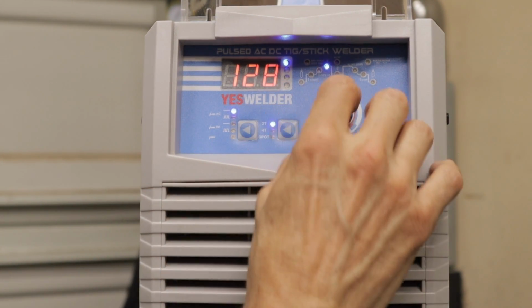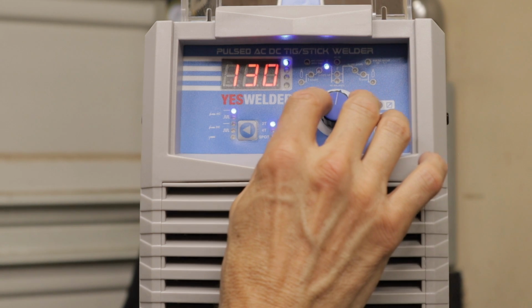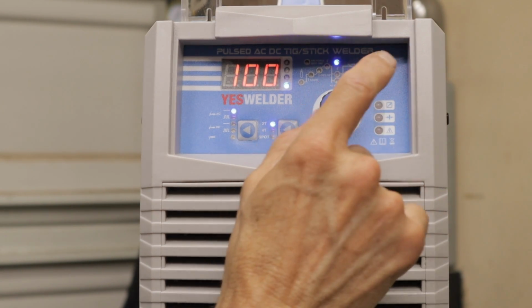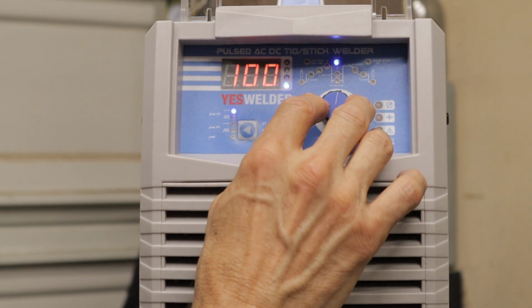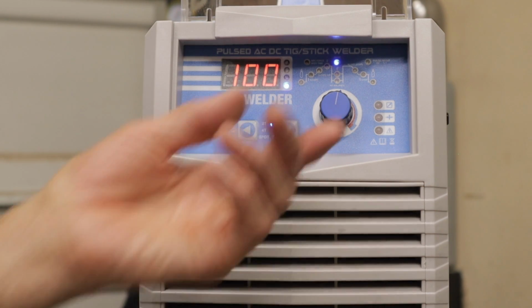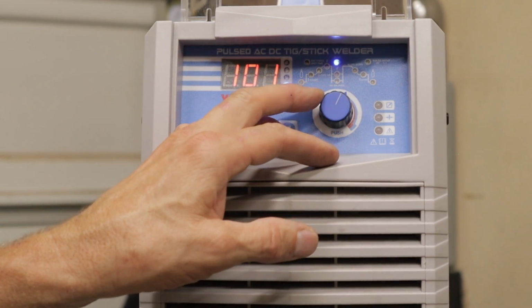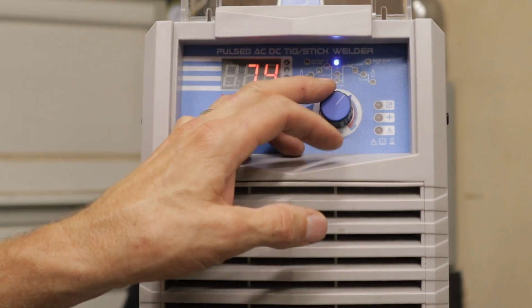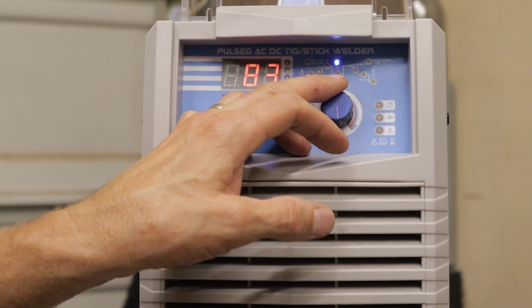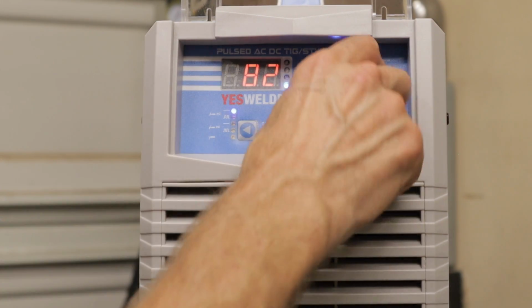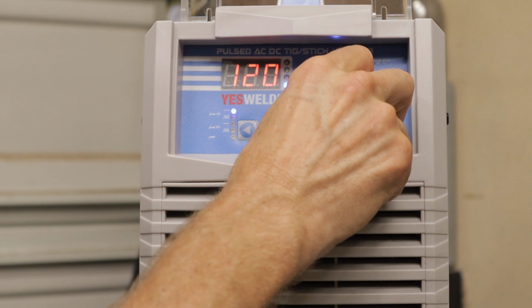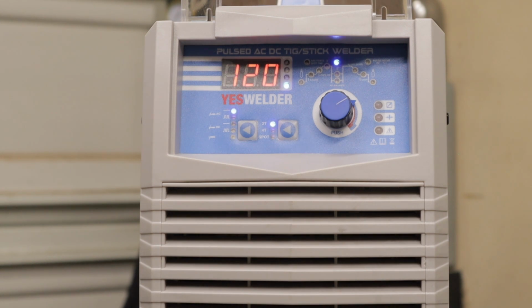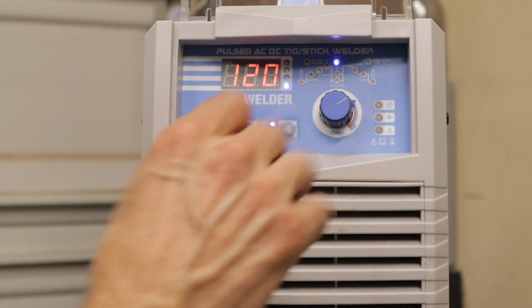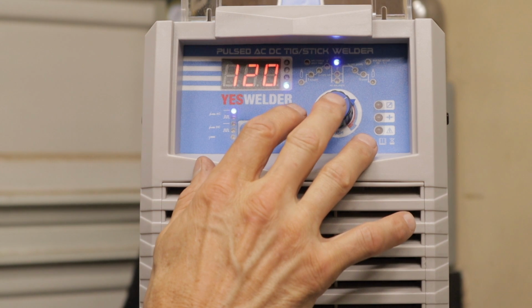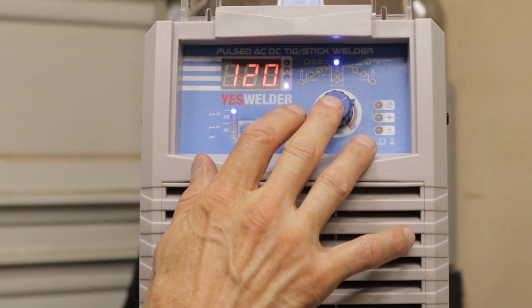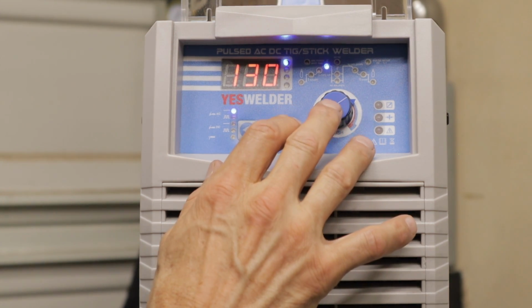Over here, obviously we already talked about the amps. If you push the button once, you'll go up to AC frequency. I have it set at 100 Hertz right now. I usually weld aluminum around 100 to 120, depending on how thick it is. If I'm welding really thick aluminum, I'll bump it down to 50 or 60. But that's how you can change your AC frequency. It's only when you're on AC.